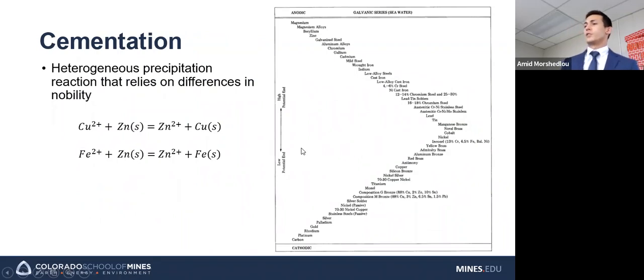And we can do the same thing with cementation. For those that don't know what cementation is, it's basically a heterogeneous precipitation reaction, and it relies on differences in nobility. So if we take a material like copper, which is very high on the galvanic series, it's more noble. We can add in a metal that is less noble, like zinc. And what will happen is we'll get a reaction that is based on those differences. Zinc will go into solution and copper will solidify as a solid. The same thing happens with iron. This is why we can use zinc to precipitate out copper and iron in solution.